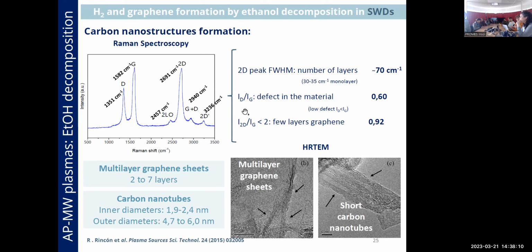And also, the number of layers can be estimated from the ratio between the intensity of the 2D band and the G band. For pure monolayer graphene, this intensity ratio is close to 2. So the closer the ratio is to 2, the better the graphene. So what we get from the Raman spectroscopy is graphene with low defects and a low number of layers, which was also supported by high resolution transmission electron microscopy.